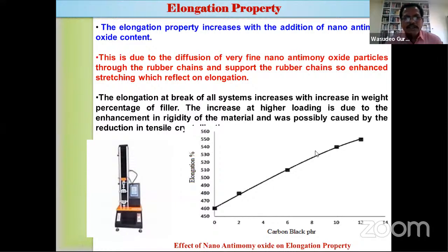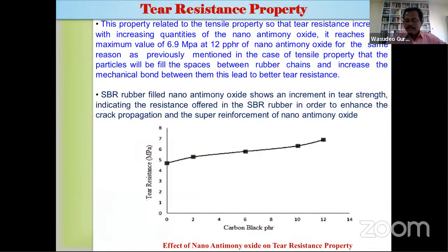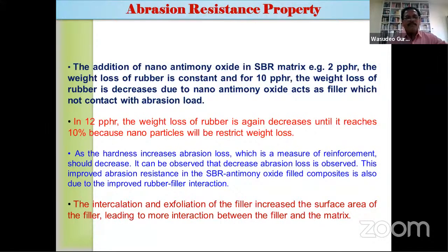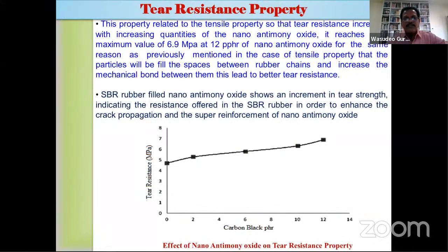And now the elongation at break increases with the increase of the percentage of filler, and the increase at higher loading is due to the enhancement in the rigidity of the material, because some of the gaps are occupied by the nanofillers, and therefore the elongation property increases. So this is another important property. And after this, it is shown in this graph how the elongation behaves.